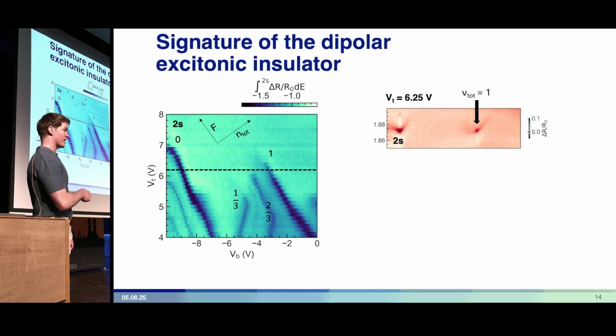So now, taking the electrostatic phase diagram and looking at a line cut at higher electric field, you can see we once again see the nu equals 0 and nu equals 1 insulating phases detected by the 2s exciton.